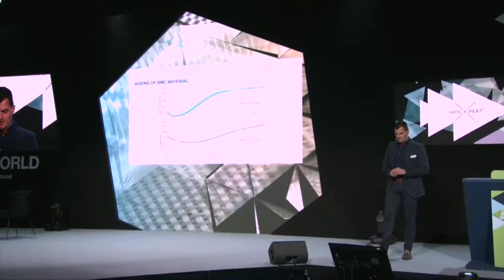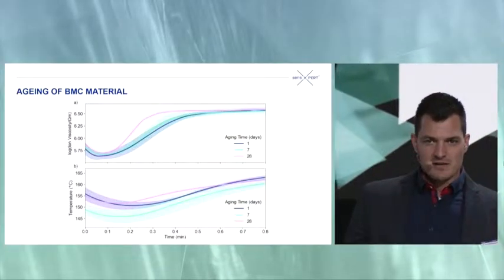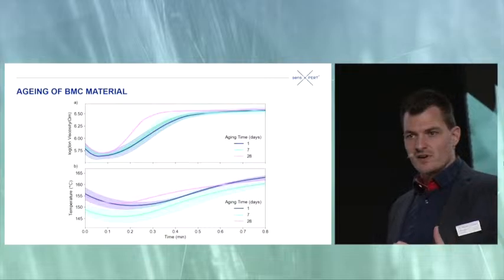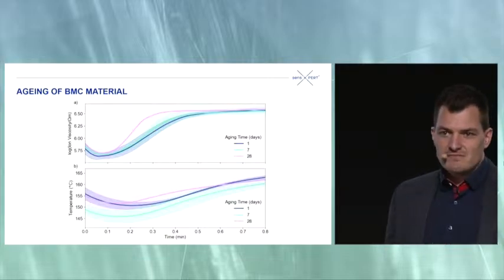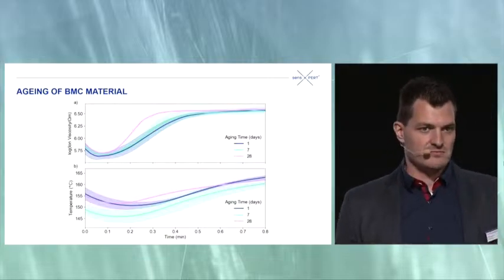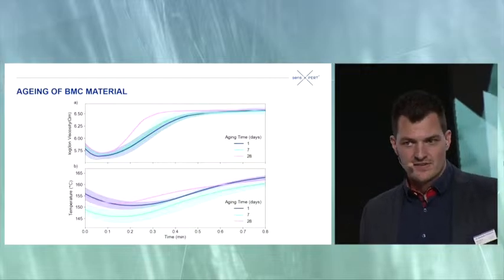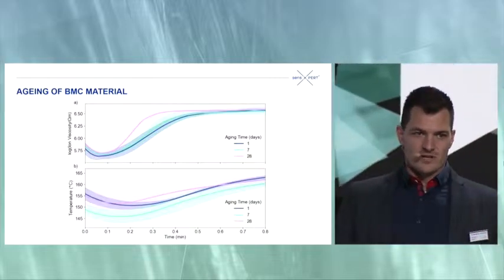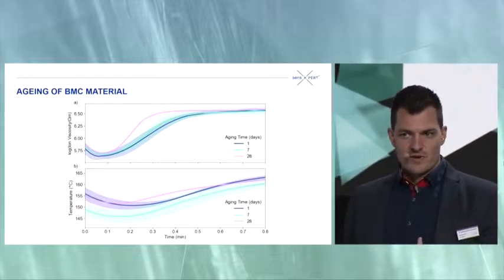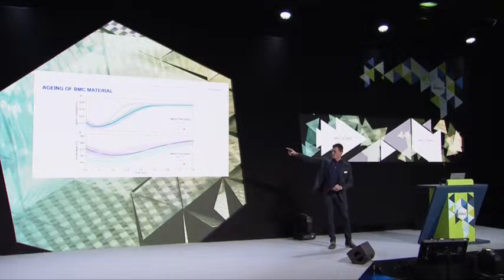Our next example here is an example of a bulk molding compound. Even there, in the bulk molding compound, we usually have a high styrene content. Again, a solvent material. This can also degas. That means the older the material, the lower is the styrene content. And that also means the older the material, the faster the curing process will be. And even the minimum viscosity is changing.